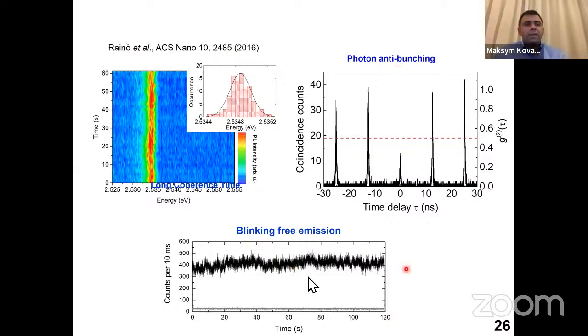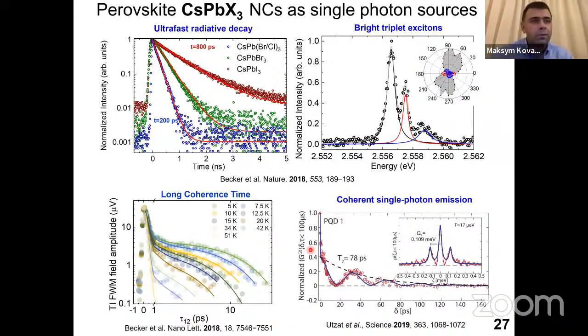So what this led us to, let's look at some other important properties, which are very specific to perovskites. One is that at low temperatures, they're extremely fast light emitters, one of the fastest emitters that you can find. Unlike conventional quantum dots, which become much slower emitters, with radiative rates in the microsecond range because they begin emitting through the dark exciton state, perovskites emit through the bright exciton state, also at low temperatures, and with sub-nanosecond radiative rates.